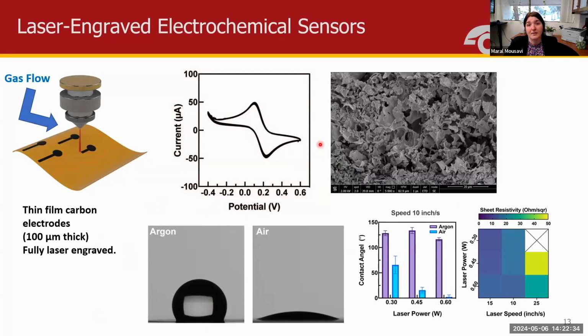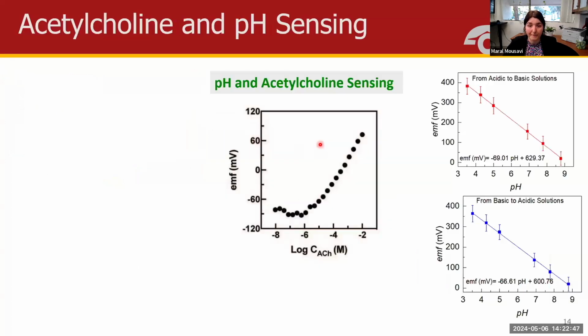The way we do the testing is modifying the lasing conditions to achieve the most conductivity and the best mechanical properties. And then we test further performance for the sensors. So a typical response that we get from these sensing modules is potential, electromotive force or EMF, versus log activity or concentration of your target ion, and you would have a linear correlation in this plot. So we look at the sensitivity, which is defined by the Nernst equation, whether this is behaving as theoretically expected or not.